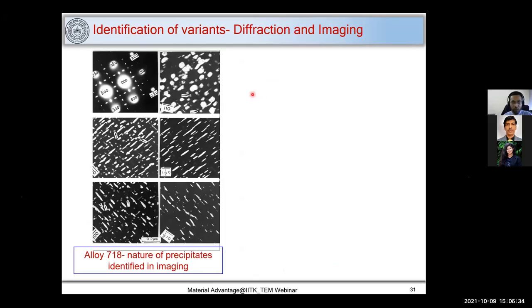Also, you can find out what the variants of precipitates are. So I have a diffraction pattern, and here, let me introduce here, I have used g equals 110. So I use this diffraction spot and I can identify which precipitates are going to give me this kind of diffraction. I can find out different precipitates, their size, their orientation, just based on bright field and dark field imaging.